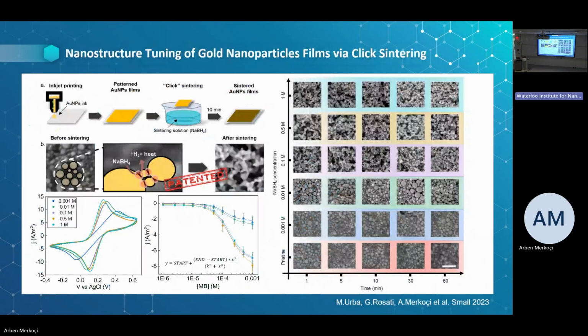So this technology indeed requires a good quality of the electrode, and this is why we have been working a lot on the improvement of the inkjet printing technology using nanoparticle-based inks. This is also a patent we applied for, in which we wanted to achieve the direct sintering of nanoparticles once you print onto any kind of surface. By using this patented technology, we are able to sinter the gold nanoparticles directly. So we achieved direct contact and sintering of these nanoparticles, and a very high conductivity, which is very, very important for our applications, as you can also see from these cyclic voltammetries.